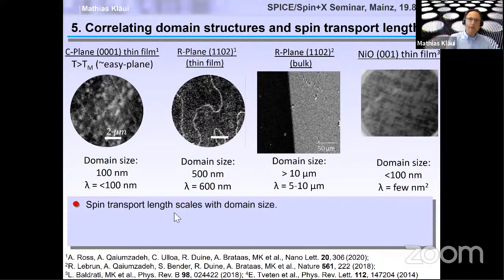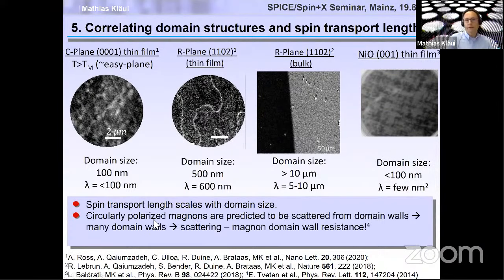So there was a theory that predicted that circularly polarized magnons should be scattered from domain walls. And if you have many domain walls, you have a lot of scattering, so you get magnon domain wall resistance. This was predicted in this paper by the group of Arne Brataas. And so this can explain our results, meaning that the domain size can govern the spin transport length scale.